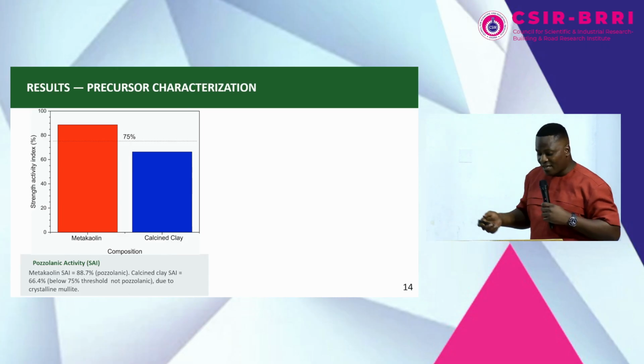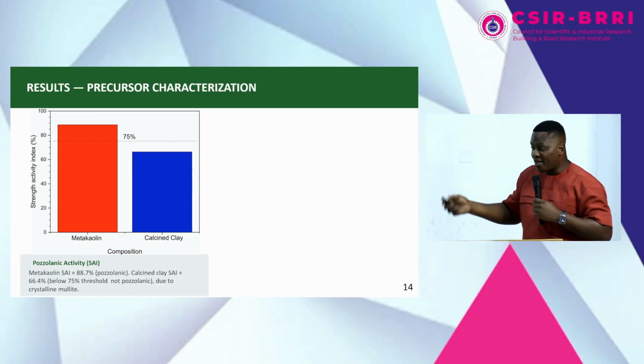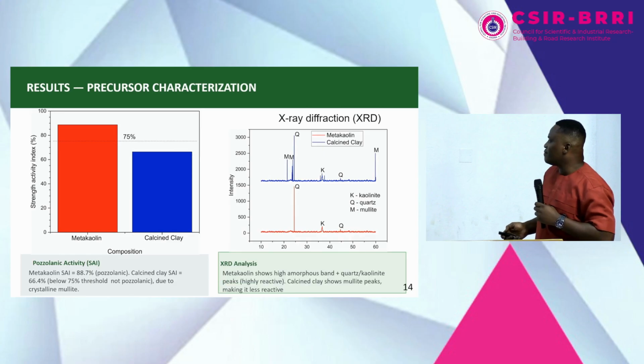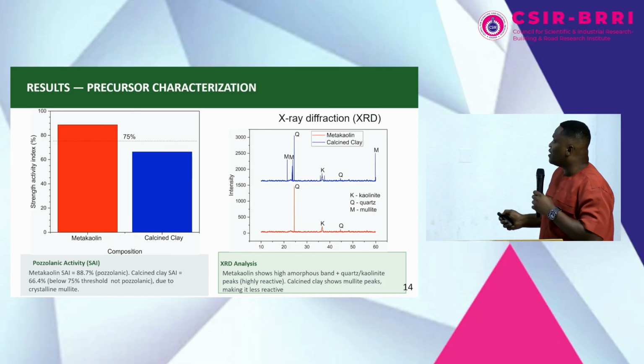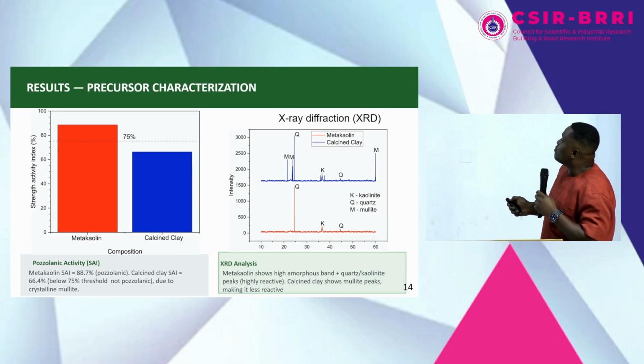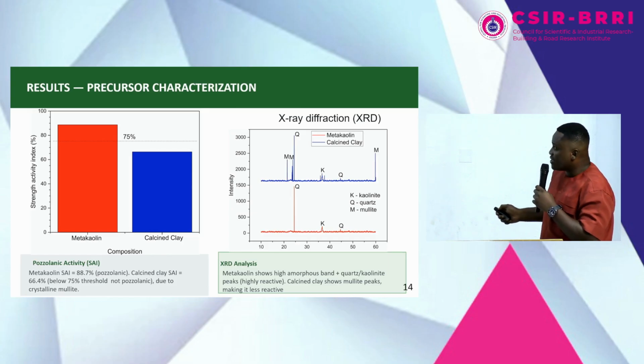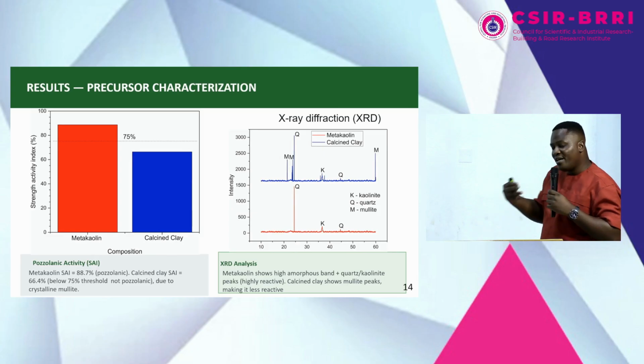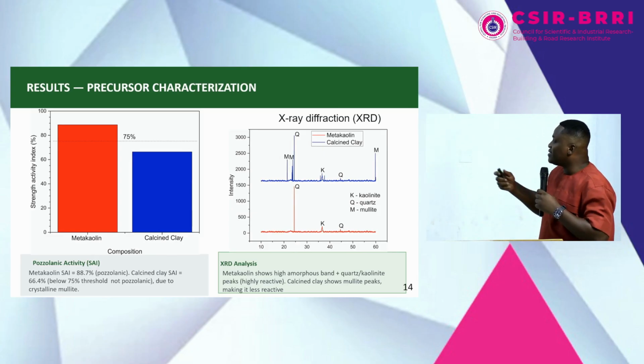So the calcined clay at this point is not performing very well compared to the metakaolin. All right, so this looks at the phases present in the two materials. We have the metakaolin here, and we have the calcined clay here. And the main difference between these two is the presence of the mullite phase in the calcined clay, because all of them have the presence of kaolin, the K representing kaolin. That's the main phase you'll be interested in when you are dealing with calcined clays.